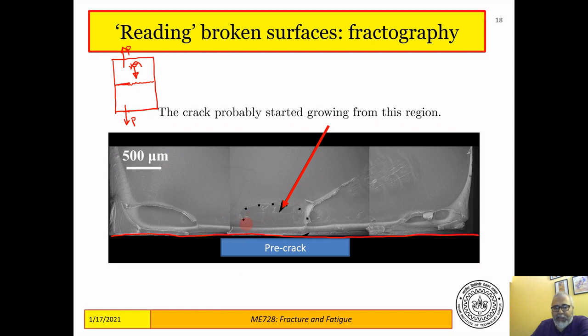And then this crack started to grow, and here you will see is a part of the surface. This is looked at under a microscope. Here is a part of the surface that looks different from the others. So you surmise that this is where the crack first started to grow. Then it grew very fast all over the place, but this is probably where the first move took place. It might have also taken place here. It might have also taken place here. So the crack started to move. This was the crack front, a long one. It started to move like this. This was the point of crack initiation, and this gives you a clue that you have to look at these locations to figure out the reasons for this failure.